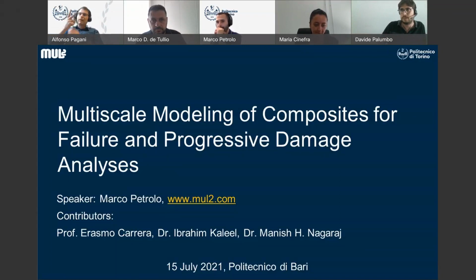Defect analysis, you're right, there are two methods generally in the literature to account for defects. One method is intrusive methods, and the second one is non-intrusive methods. In intrusive methods, you change your mathematical model, or in other words, you change the mesh, right? So you are able also to account for directionality and progression of failure and so on. The second method is non-intrusive, in which you put the defects as a homogeneous property. For example, you can use a penalty to penalize the stiffness of the material in a given point.